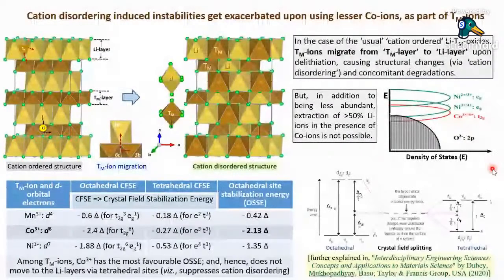Now, the problem that happens with most layered lithium transition metal oxides, especially if we want to replace cobalt with some other transition metal, is that when more and more lithium is taken out, the nice cation-ordered structure becomes a cation-disordered structure. This transition takes place via an intermediate tetrahedral site. So the nickel ion in the transition metal layer, in the case of lithium NMC, moves from its original octahedral site in the transition metal layer to an intermediate tetrahedral site, and then to the octahedral site in the lithium layer.